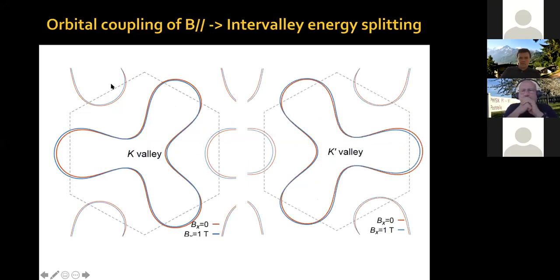If you look at the electronic structure at the Fermi surfaces, these are what the Fermi surfaces of magic angle graphene look like. You see that they have this threefold rotational symmetry for one valley and for the other valley. So for this nesting of Fermi surfaces, you expect a threefold rotation symmetry. But what we see are ellipses, not threefold rotationally symmetric structures. So the system is choosing one particular direction. When the system has several options to choose from but ends up choosing one particular direction, that means the response of the system is nematic. That's a change from C3 symmetry to C2 symmetry, if you include both valleys. C2 symmetry means nematicity.